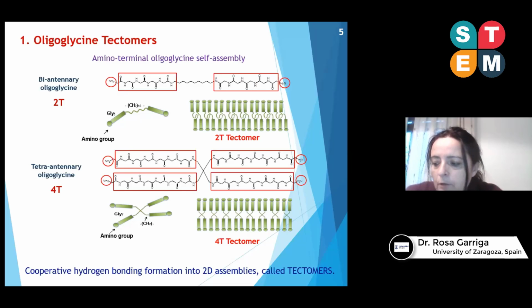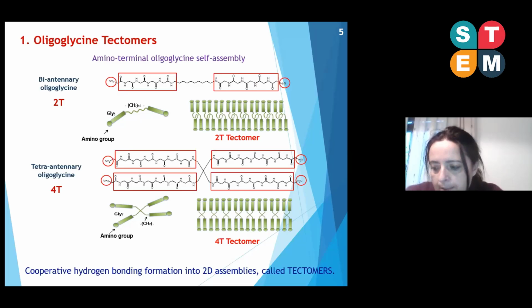Interestingly, though tectomer formation can take place in solution, it has been reported that the assembly process proceeds 2 orders of magnitude more rapidly on a mica surface. pH shifting towards alkaline conditions triggers the deprotonation of terminal amino groups and the loss of the associated electrostatic repulsion, resulting in extended tectomer formation.